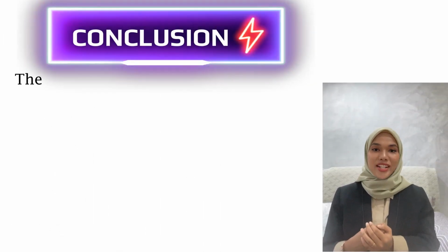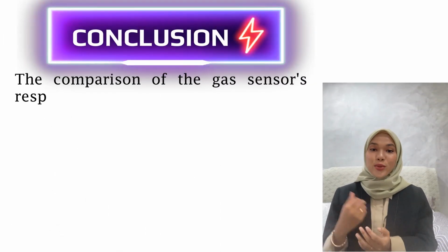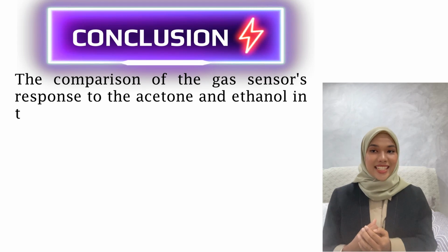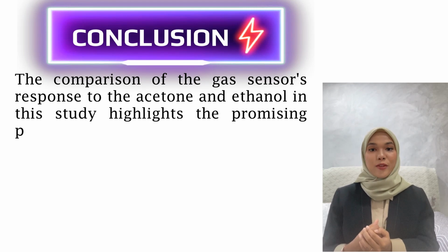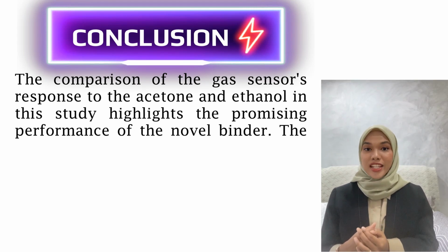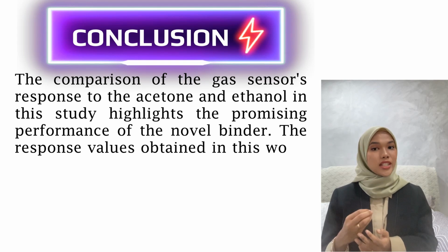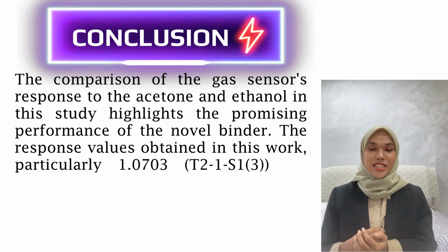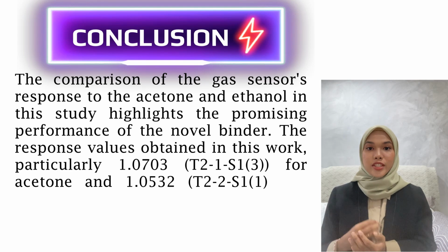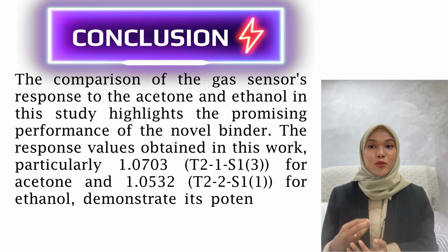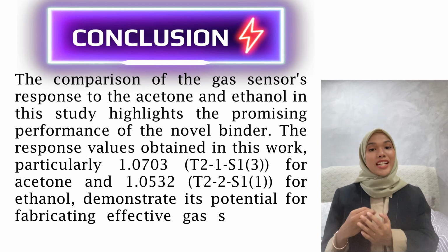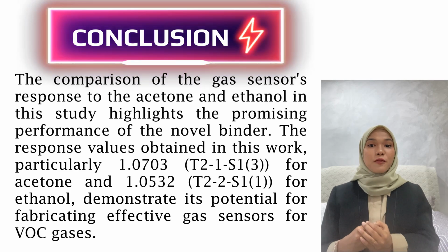Conclusion: the comparison of the gas sensor response to acetone and ethanol in this study highlights the promising performance of the novel binder. The response values obtained in this work, particularly 1.0703 for acetone and 1.0532 for ethanol, demonstrate its potential for fabricating an effective gas sensor for VOC gases.